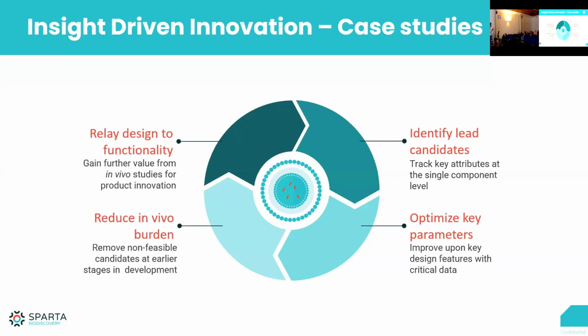But when we take these formulations further, we might get, for instance, challenges in scaling up of formulations. So you're making this with a pipette or with a very small scale reaction in a lab. But in order for it to be a successful formulation in industry, we need to make this on liter scale, right? Or tens of liter scale, these formulations. And we use completely different reactors or different techniques to make that. And this can, again, cause variation in the composition. So we work with companies, for instance, that are scaling up this production to then test, okay, how do these different production methods actually interfere with the variation, and do I have the same formulation still that I've made?